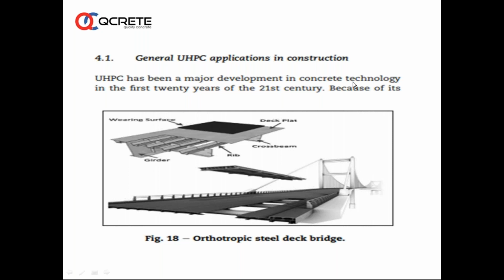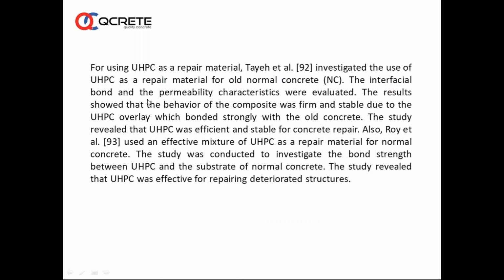UHPC has been a major development in concrete technology in the first 20 years of the 21st century. A bridge deck, you can see, for using UHPC as a repair material. People have investigated UHPC as a repair material. The interfacial bond and the permeability characteristics were evaluated. The results showed that the behavior of the composite was firm and stable due to the UHPC overlay.